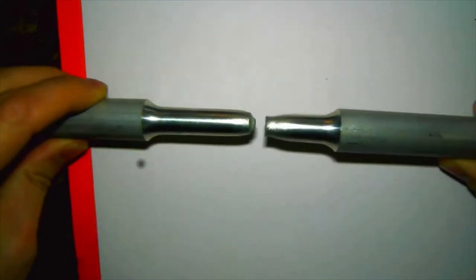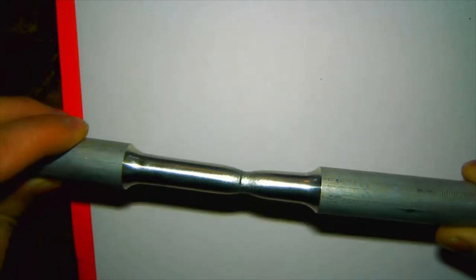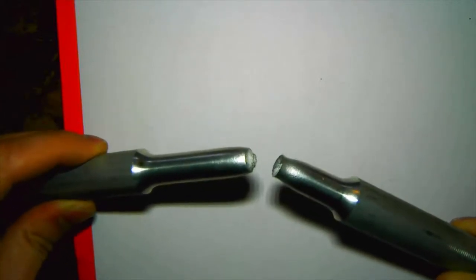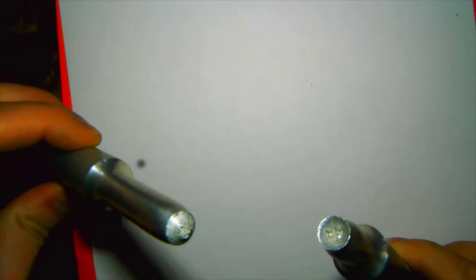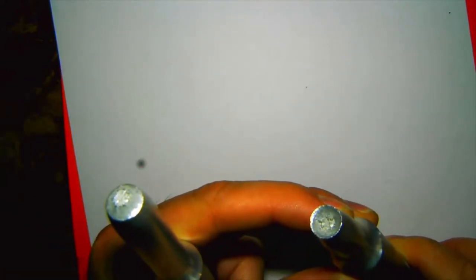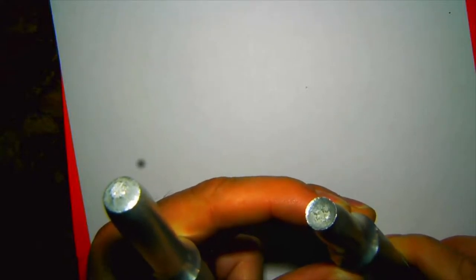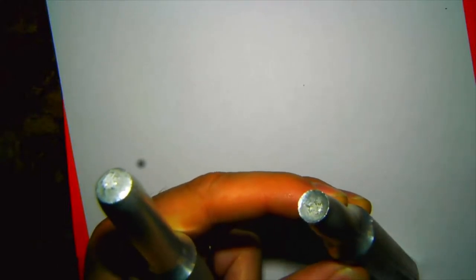Here's an aluminum dog bone — or aluminum tensile test specimen. When it was pulled, it started to neck, so you can see a narrowing region, and then it formed a cup-cone fracture surface, which is typical of ductile fracture. If you look closely, you can see some roughness on the surface — that roughness is actually grains sliding relative to each other. This is an example of how granularity can affect failure surfaces. You'll do something similar in your tension test lab.